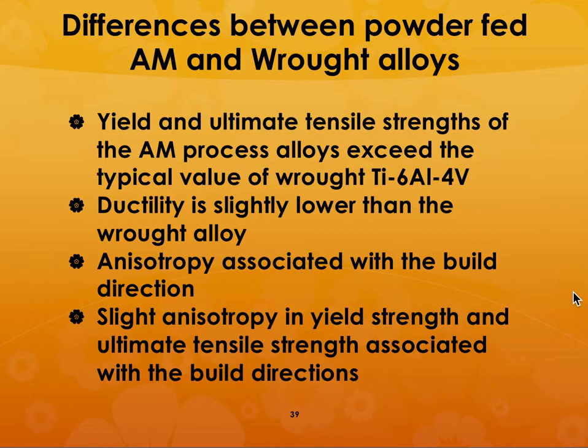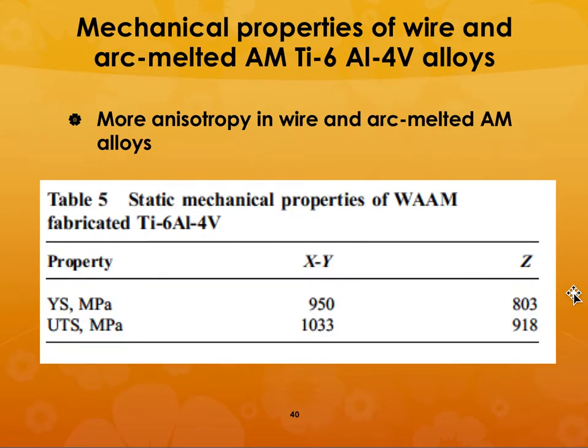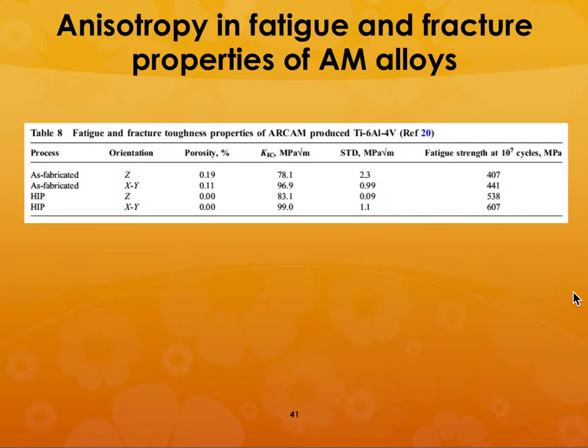So because the strength is higher and the yield strength is higher, the ductility is slightly lower than the wrought alloy. And there is anisotropy associated with the build direction, and there is slight anisotropy in yield strength and ultimate tensile strength associated with the build directions. So this is what I have said.